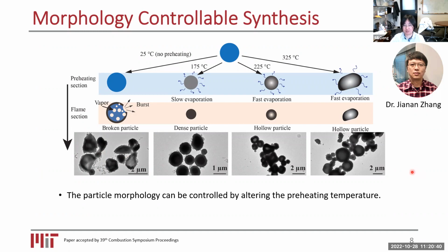So I'm not sure if things are shown on your end very clearly, so we can focus on this schematic to give you an idea of what happens. So what really happens is that if there's no preheating section, we directly spray things into the flame. We will end up with these broken particles, meaning that they do not have very good integrity and the mechanical strength is weak. So you can imagine after we combine them with other materials, the performance would get impacted.